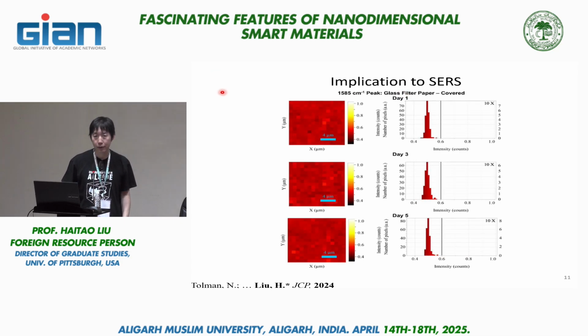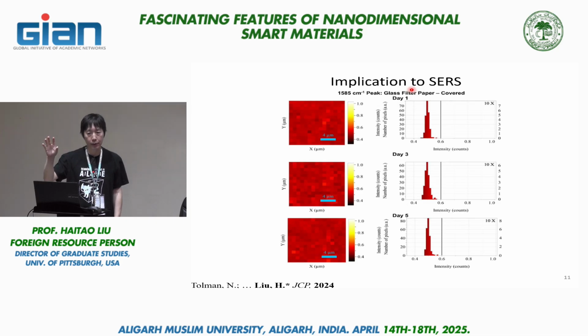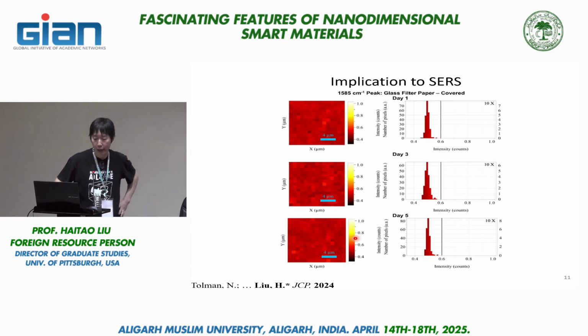Now the more interesting result is this one. This is very unexpected. So we did the same thing. We make a SERS substrate, we leave it in air for a couple of days, except in this case, we cover it, so we put it in a glass vial. We leave the vial open and lay flat so air can go through. In this one, we cover everything with a glass filter paper. And surprisingly, now we do not see those Raman signatures anymore. This is totally counterintuitive to us, and we do not understand fully what this means. But the data seems to suggest that everything we saw, in this case at least, comes from pretty large clusters.